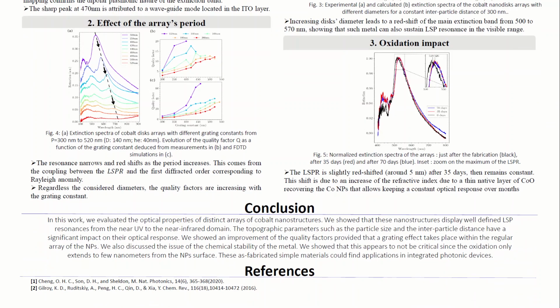In summary, we evaluated the optical response of cobalt nanostructures. We showed that they can display well-defined LSPR in the visible range. The morphological parameters have a significant impact on this resonance. We also achieved an improvement of the quality factor by taking advantage of the grating effect. We addressed the question of chemical stability, which seems to not be critical since we have a passivating thin layer on the cobalt nanoparticles that keeps the optical response constant.